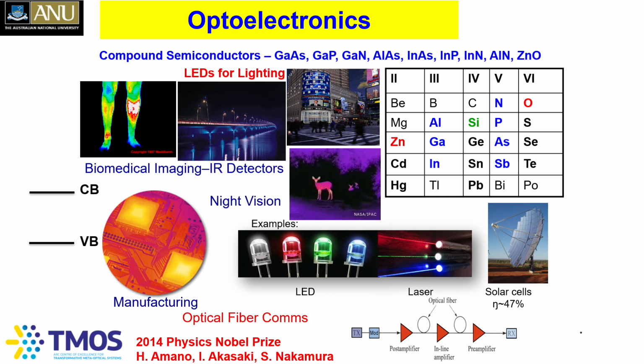But unfortunately, silicon is not a very good light emitter because of its indirect band gap nature. So you need to have direct band gap semiconductors to emit light. That's where we end up using group III-V semiconductors: gallium arsenide, indium phosphide, gallium nitride, and a combination of these materials. And the development of the nitride technologies, which led to the blue LEDs, which was a missing link till the 90s or so, has led to the Nobel Prize for these three Japanese scientists.